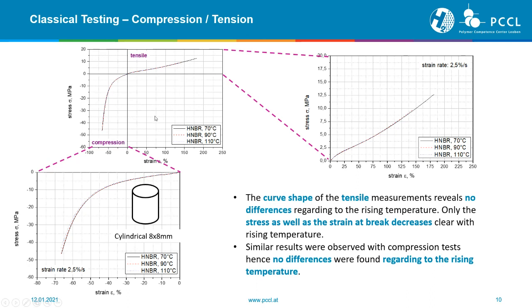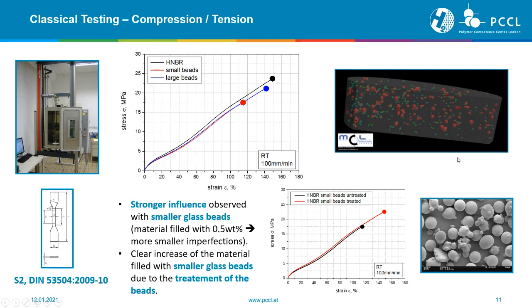What you also can see here is that we've implemented these tests at different temperatures, 70 to 110, for compression as well as for tension. And what we see here is that the influence or the impact of this test temperature, 70 and 110, is not really that big on these test results. The only difference we can see here is that we have a little bit of a decrease in the stress and strain at break when we increase the temperature.